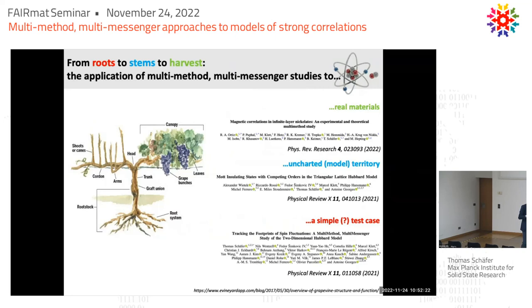For example, also for FRG, they use some momentum grids or some schemes where it expands in the momentum, and some of them will simply not work anymore. But I would consider this a more technical issue. On the other hand, from the algorithm's point of view, if you take DMFT, the approximation is much better in three dimensions, because three dimensions turns out to be much closer to infinite dimensions than two. Much closer.